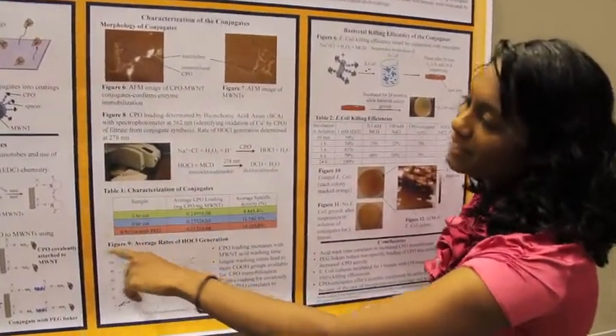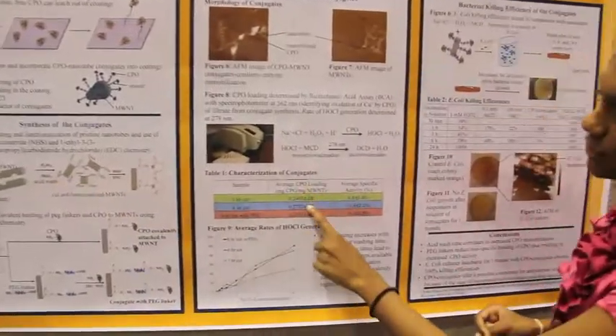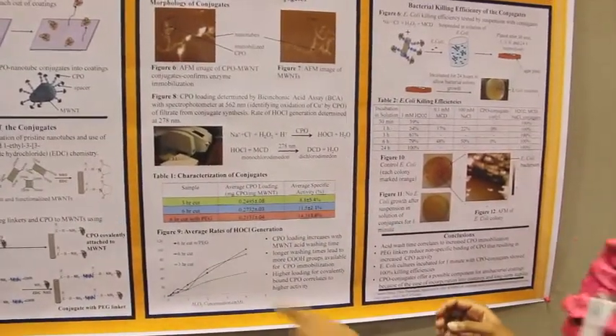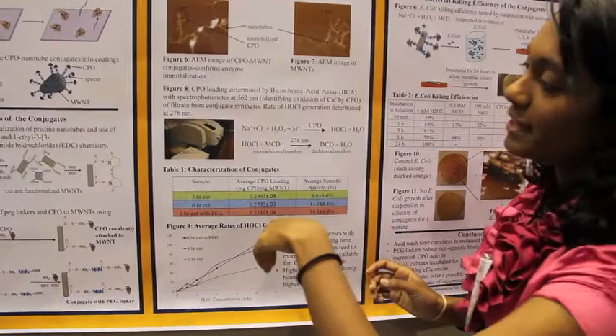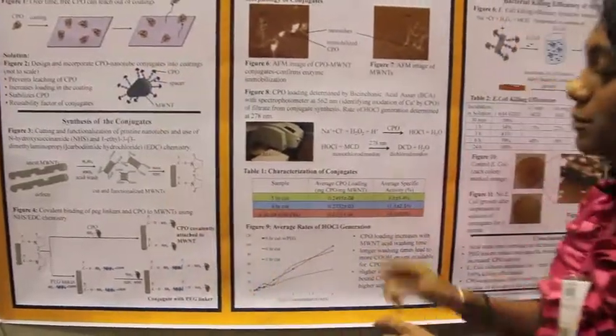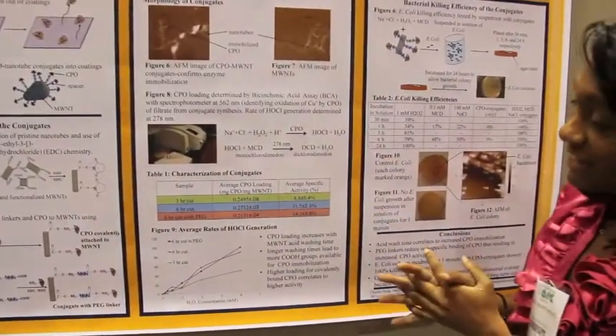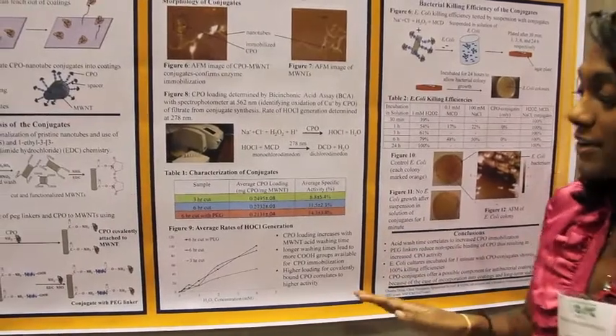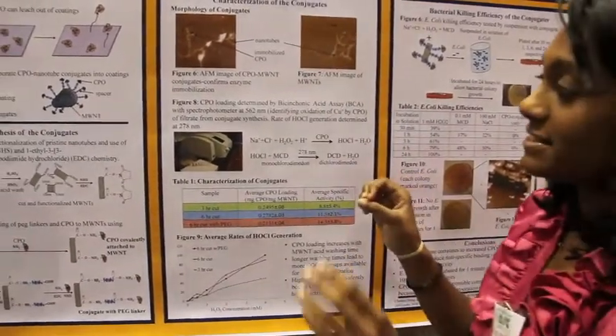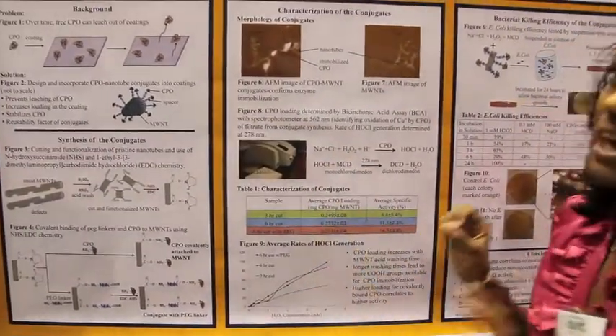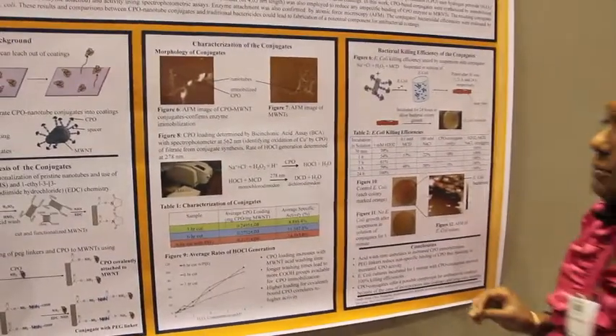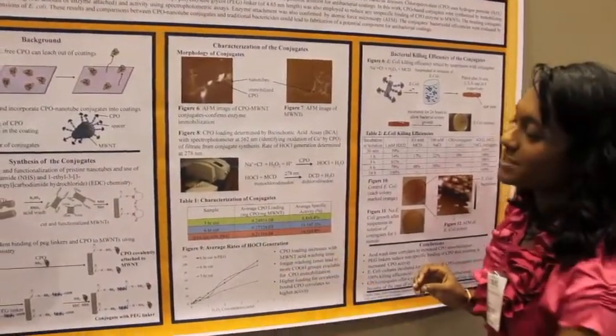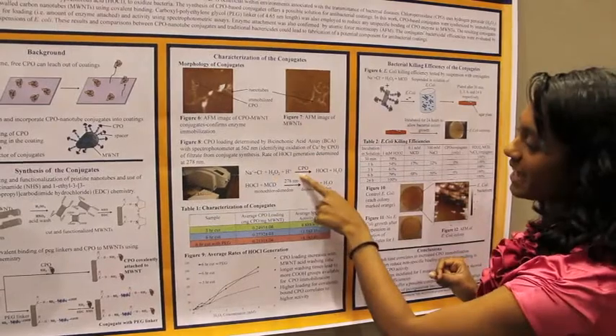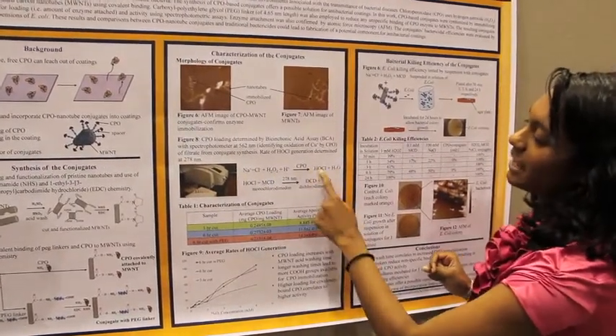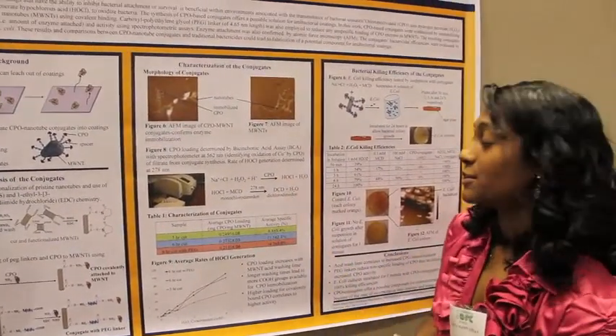And we found that with increased cutting time by acid wash, the loading would increase, so would the activity. But whenever we added PEG linkers, the amount of enzyme loaded onto the nanotube would decrease, but the activity would actually increase. So this is very good. That means the enzymes are not deactivating as much on the nanotubes. And we also found out how much hypochlorous acid was being generated using this reaction. And because basically hypochlorous acid is what the antibacterial component is.